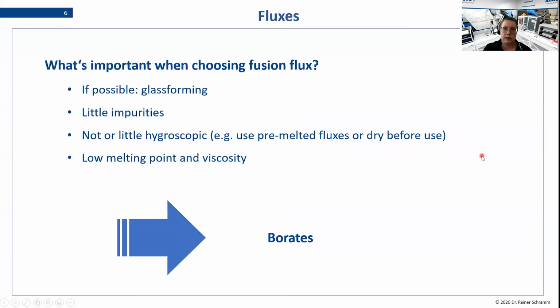So now fluxes. What's important when you are choosing your fusion flux for your process? First of all, if possible, we want the flux to be glass forming, because in the end we want to have a glass. Then you want the flux to have few impurities because this is your diluent. Every impurity that you see in your diluent, you will later see in your measurement, in your analysis, and you might have to correct for them later. So you try to have just few impurities in your fusion flux.